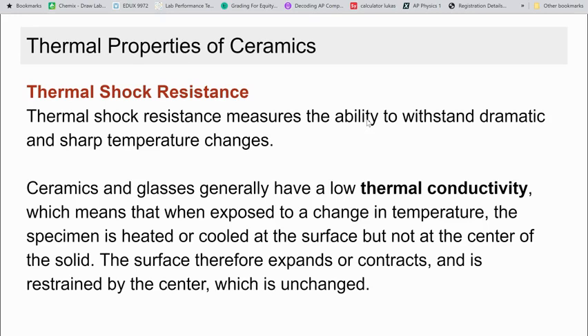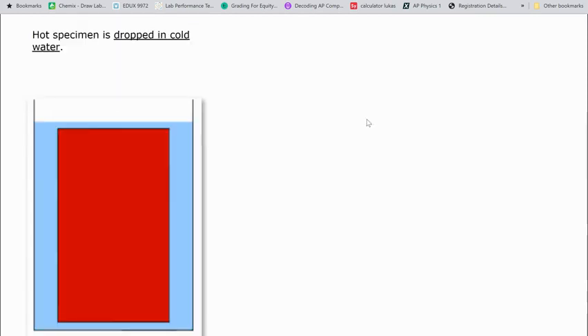Thermal shock resistance is the ability to withstand dramatic and sharp temperature changes. Ceramics and glasses generally have a low thermal conductivity. So what that means is when they're exposed to a rapid change in temperature, the specimen is heated or cooled at the surface, but because the thermal conductivity is not good, it doesn't change the center of the solid. Therefore, the surface of the material expands or contracts and is restrained by the center, which is unchanged. This is why ceramics, if exposed to wide, fast, quick changes in temperature, often become brittle and break.